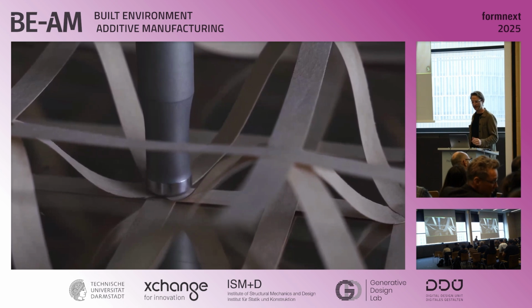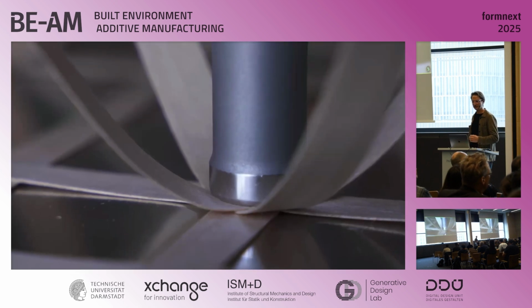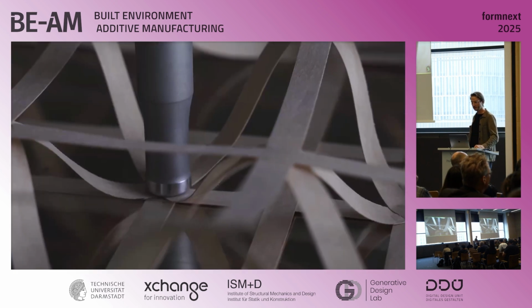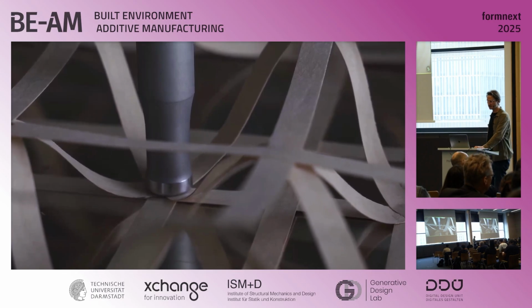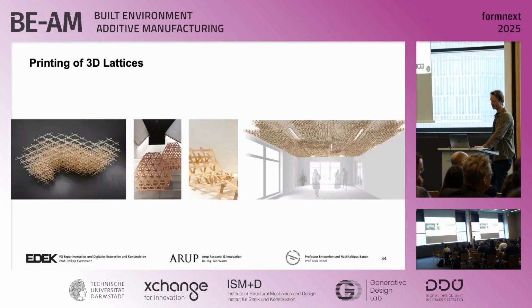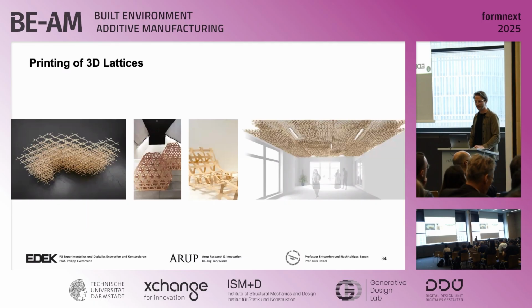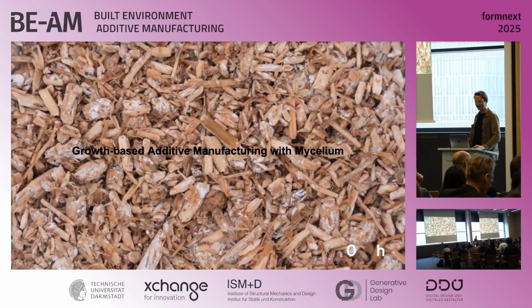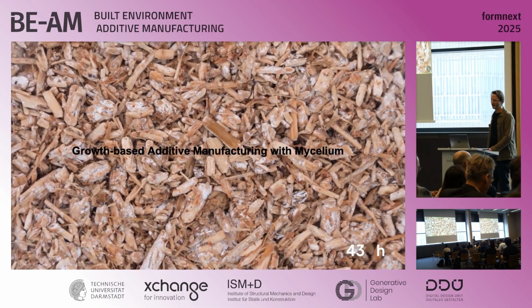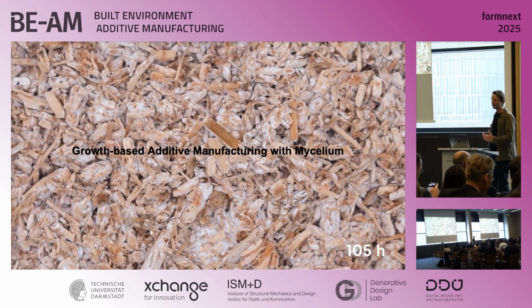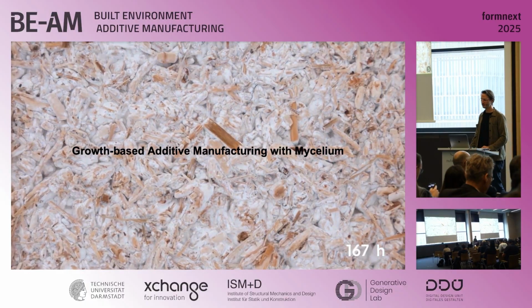And you turn this kinetic energy into thermal energy, melting the lignin in the wood, and this becomes the adhesive. And we were looking at these lattices, which were quite interesting, for how to use them in architecture, and that's where mycelium comes into play. That's a material we have been researching for around 5 years.